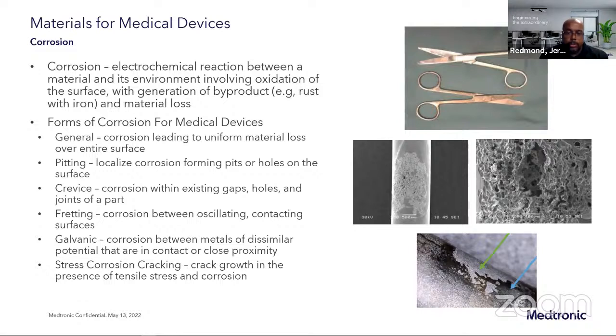And then the final one there is just stress corrosion cracking. This is where we can have pre-existing defects or cracks at a microscopic scale. But under a stress condition, those cracks may be stable, but through being put into an environment where there's also a corrosive medium or an activity where you can get corrosion, you can have those cracks actually accelerate in their growth as a result of both the combination of stress and corrosion.